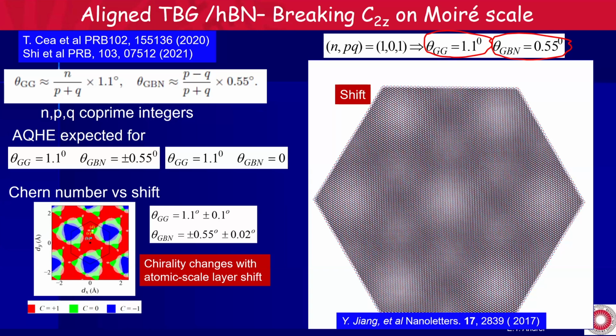Okay, and as Allan noticed, what he plots here is the chirality. So red is Chern number +1, blue is -1, green is 0, and the scales here are an offset from perfect alignment in angstroms, in the x direction and y direction. So if you're off by an angstrom from the center to the right, you end up with Chern number 0. If you're off by an angstrom and a half, your Chern number is -1. So then the question is, how come these people doing transport over a macroscopic sample, a few microns, which for us is macroscopic, were able to observe the quantum anomalous Hall effect? What was going on? So that's what motivated us to look into it with scanning tunneling microscopy.